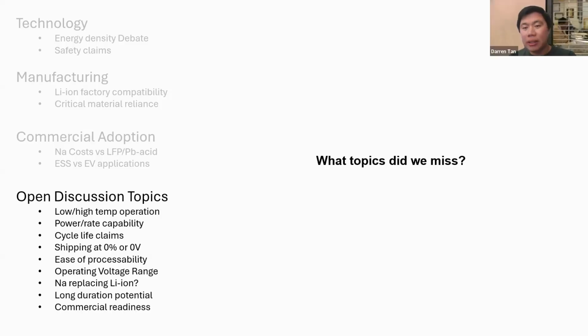Yes. So that's actually a complicated question. So we know in lithium-ion batteries, you cannot ship at 0% or 0 volt, right? You always ship at 30%. And the technical reason for that is because of the copper foil. So copper dissolves into electrolyte, and if your cell voltage goes below a certain point, it will precipitate on both your electrodes, and that poisons the battery and cause your cell to die a lot quicker. That's why most lithium-ion batteries are shipped at 30% based on UN 38.3 requirements. Now, sodium-ion batteries have no copper foil. Both sides are aluminum foil, so you don't have this copper dissolution problem. So you are free to ship it at 0%.